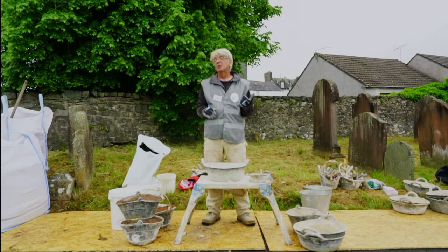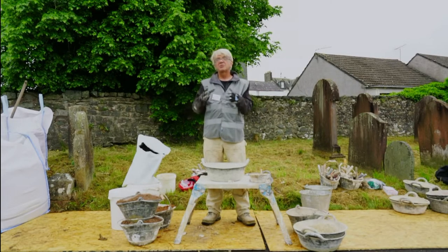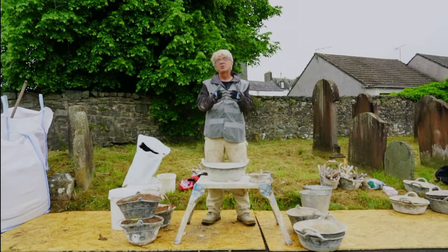They didn't draw any conclusions from what they saw. I did. They showed that the 1:3:12 cement lime mortar had 6 times the water retentivity of the most water retentive of the NHLs they tested. 6 times is a big difference. And that's exactly what the US Bureau of Standards were aiming to achieve.